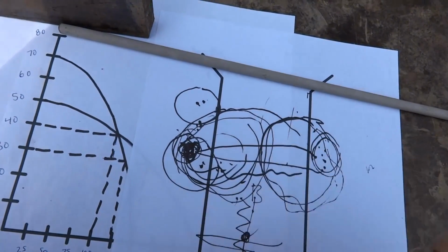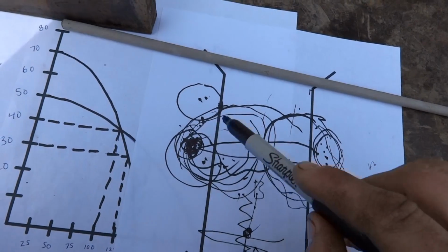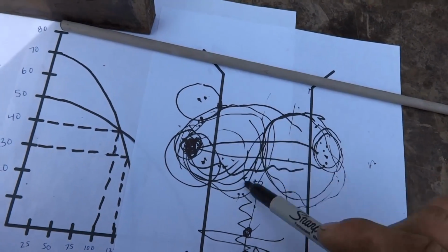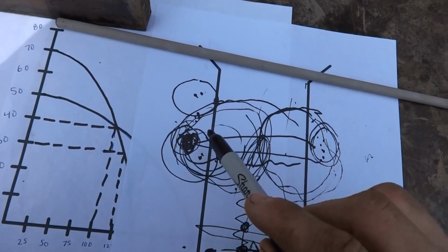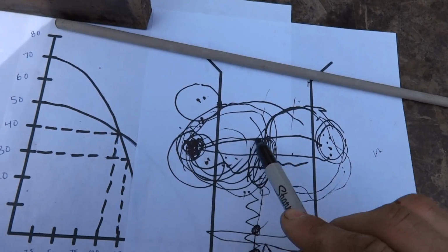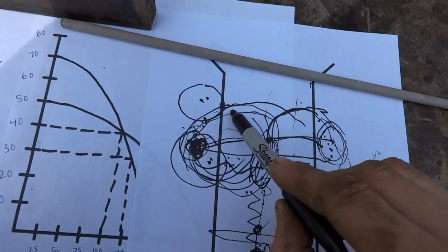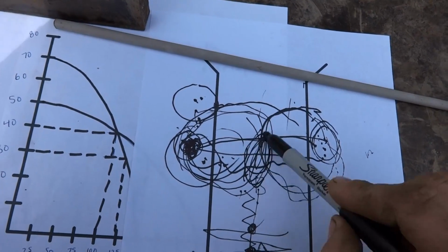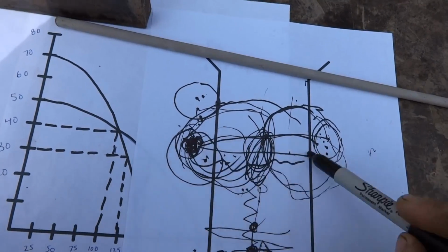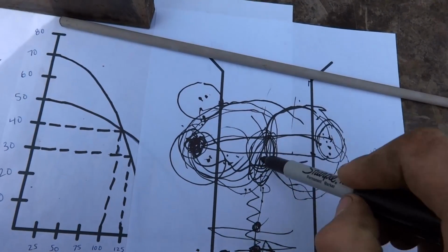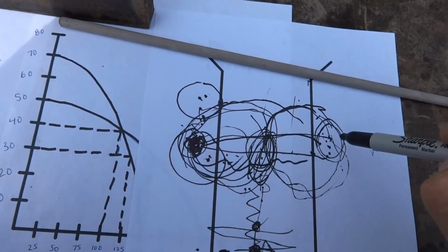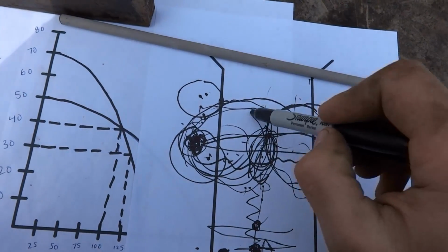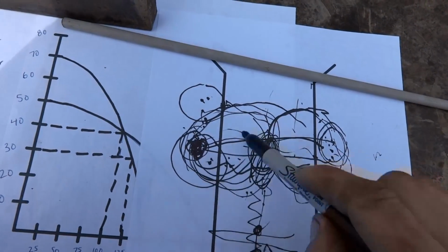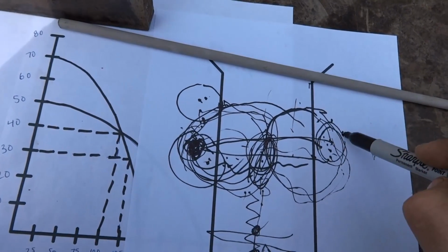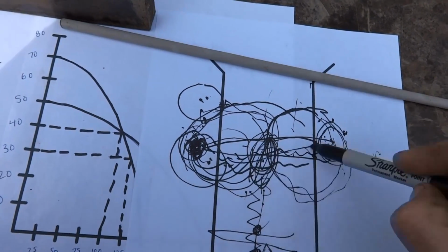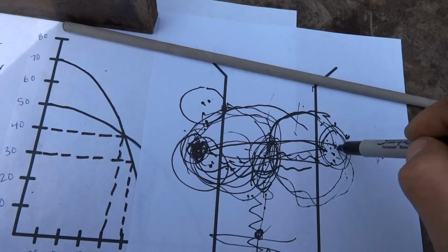I covered porosity. I covered burn through. You see, you're not going to blow a big hole in the middle here because it solidifies from the left hand side. It starts to solidify when you go to the right hand side. It starts to solidify when you go back to the left hand side. The heat is not going to collect. Your puddle is not going to remain liquid, and you're not going to blow a big hole in the middle of the pipe here because your puddle solidifies as it follows you. It's not liquid back here while you are over here. It is solidified and it's on its way to follow you. That's running the high amperage and low voltage setting.